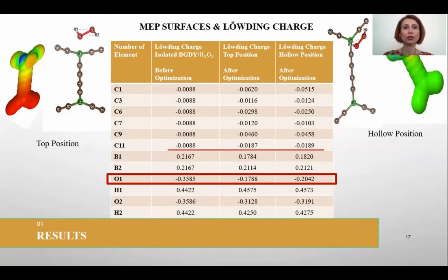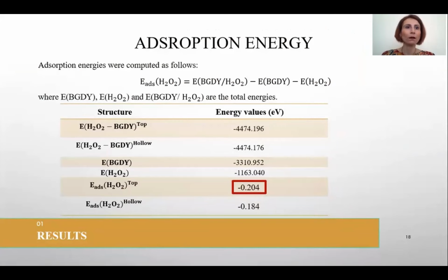Before and after optimization, the changes of Löwdin charges for both hydrogen peroxide and boron graphdiyne are listed. Löwdin charge shows the carbon atoms near the boron are negatively charged, and hydrogen peroxide interacts with boron graphdiyne through the first oxygen atom of hydrogen peroxide. Adsorption energy can be defined as the decrease in energy while two materials are combined under the adsorption process. Adsorption energy at the top position is bigger than at the hollow position, which means that breaking the bonds between hydrogen peroxide and boron graphdiyne for the top position needs more energy.